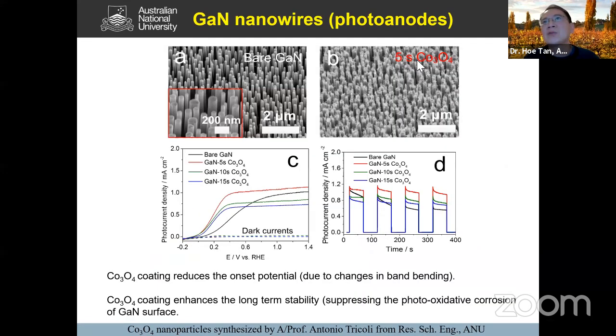So you can see here, we deposit cobalt oxide nanoparticles. 5S means 5 seconds of deposition. And if you look at the red curve here, so by putting some cobalt oxide, you can see the photocurrent is enhanced. Okay. And in addition to that, you can see the onset potential now is reduced. Okay, which means the external bias that we apply to this system, we can reduce the applied potential. Okay, but if you deposit too much cobalt oxide, for example, 10 seconds or 15 seconds, then it starts to cover up some of the gallium nitride nanowire and it blocks out some of the sunlight. Okay, so that's why the photocurrent drops again.